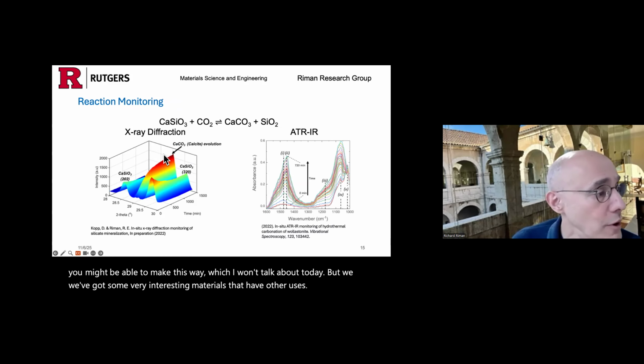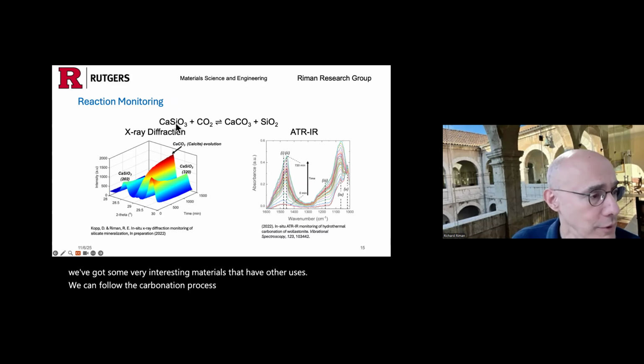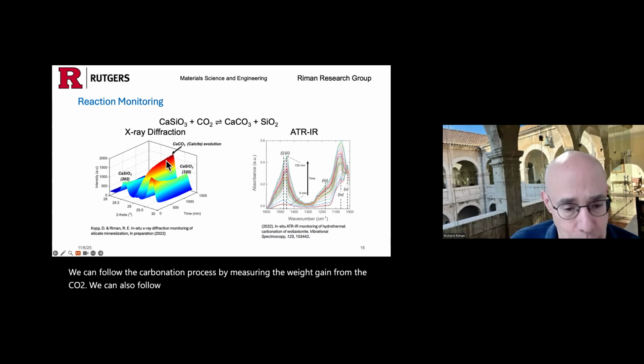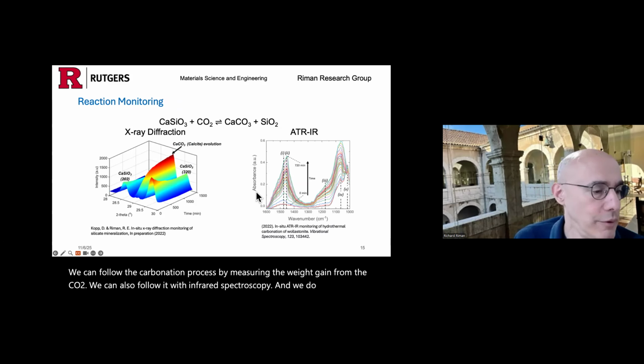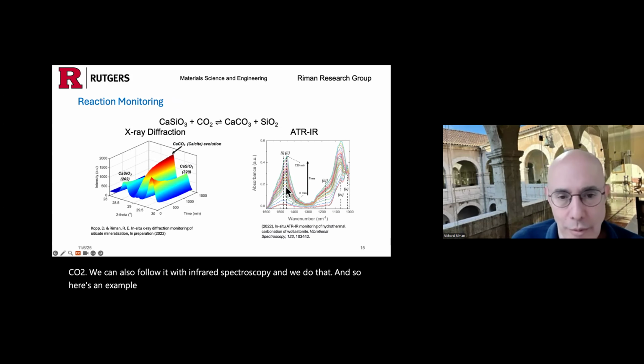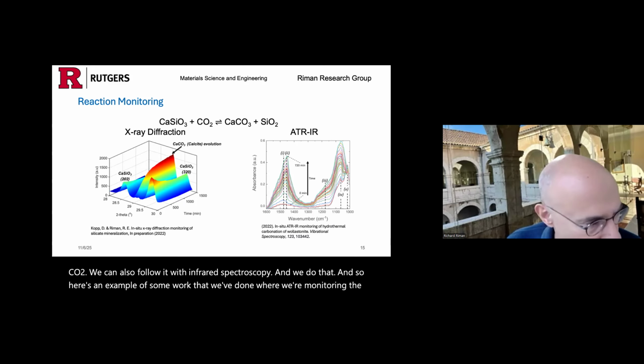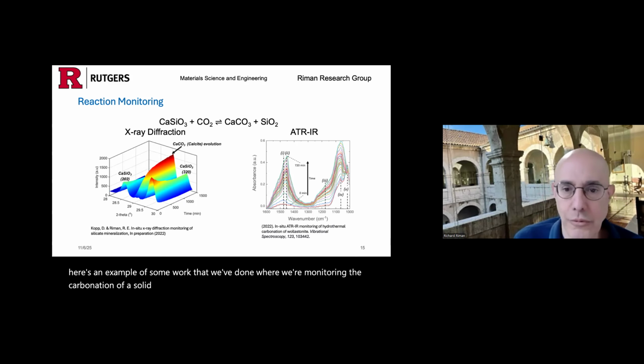We can follow the carbonation process by measuring the weight gain from the CO2. We can also follow it with infrared spectroscopy. And we do that. And so here's an example of some work that we've done where we're monitoring the carbonation of a solid in situ while curing the material.